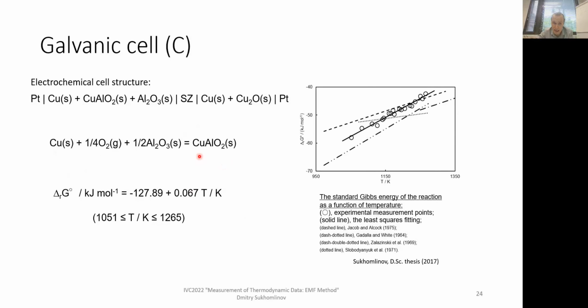Galvanic cell C with CuAlO2 phase and aluminum. Here is the virtual cell reaction, and here a solid reference electrode was used. Metallic copper and Cu2O. And the Gibbs energy of this reaction was measured like that.